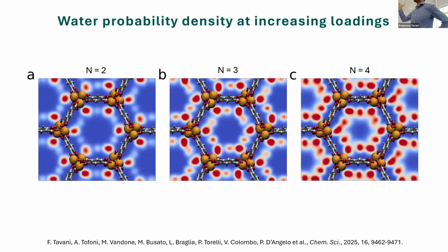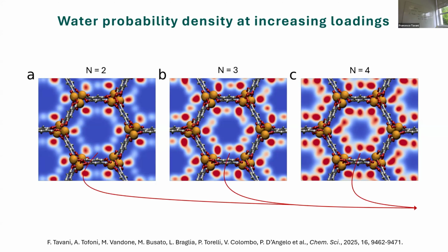So we also calculated water probability density maps at increasing water loading. So you may see, again, we're highlighting in red the regions where the water molecules are present with higher probability. And as you increase the water loading, you can observe that here, for example, and here there is an increasingly higher probability of finding water molecules.